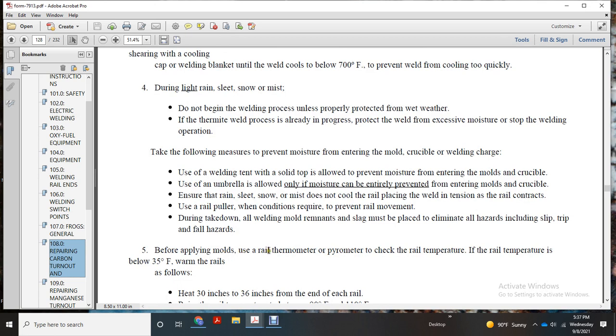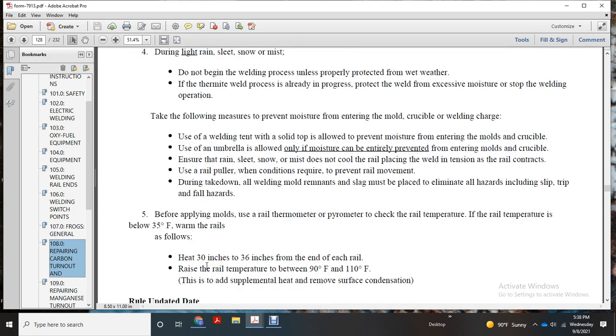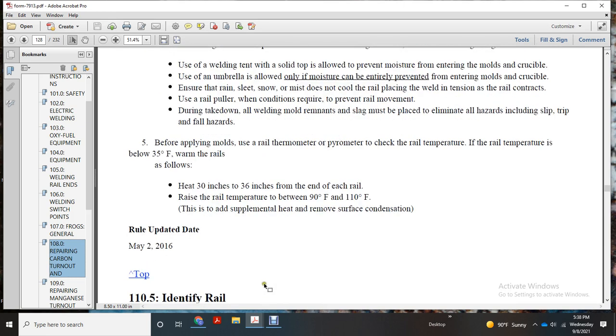Before applying molds, use a rail thermometer or pyrometer to check the rail temperature. If the rail temperature is below 35 degrees Fahrenheit, warm the rails as follows. Heat 30 inches to 36 inches at the end of each rail, until the rail temperature is between 90 and 110 degrees Fahrenheit. If supplemental heat was added, remove any surface condensation.